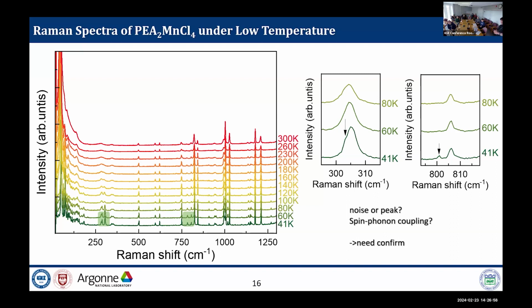Also, there is a new peak arising near 800 per centimeter. In this calculation and more experiments, it seems like a new vibration mode due to some interaction between the inorganic octahedra and the organic cation, because near this peak is the location of NH3, CCC or CCN, or CC single bond stretching or wagging modes. So this means there is some coupling between the metal halide magnetism and the organic molecule. The peak could be understood this way, but we haven't confirmed that this is a real peak. So it needs more low temperature experiments and confirmation, but this is a very interesting result if this is a real peak. So this is one kind of evidence of spin-phonon coupling.